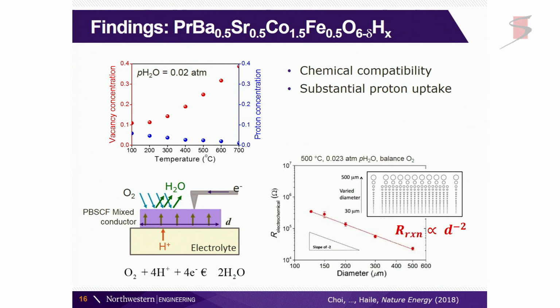And we did an experiment where we wanted to establish that, in fact, the entire surface is electrochemically active. And we did that by micropatterning a number of these microdot electrodes on top of the proton conducting electrolyte, measured the electrochemical reaction resistance here, and observed that this scales with area. And that demonstrates to us that this is active over the entire surface.